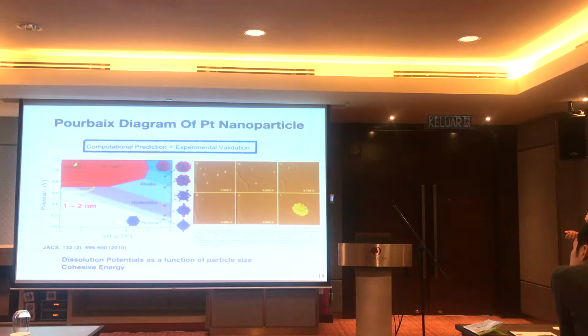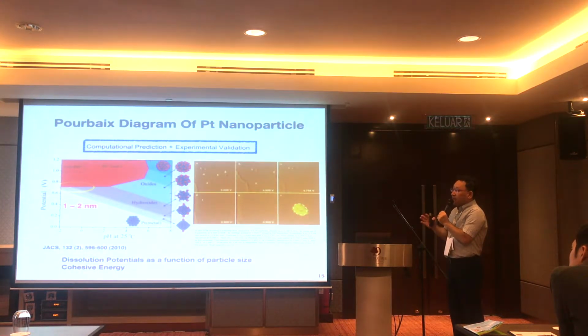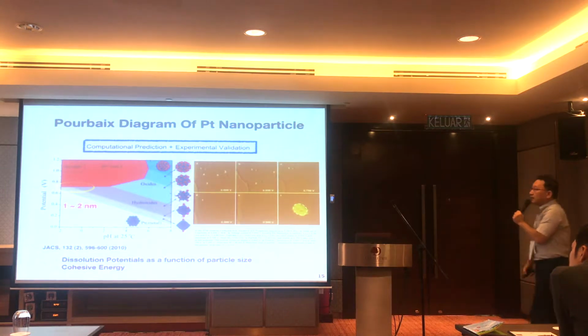This picture shows that platinum nanoparticles dissolve at 0.7 volt. In the meantime, bulk platinum, the wedding ring, right, dissolves only in strong acid solutions. They only dissolve above 1 volt with respect to the standard hydrogen electrode. But a nanoparticle of this size starts to dissolve at 0.7 volt, which means there is a huge decrease in the electrochemical stability, right? You know that electric vehicles driven by hydrogen utilize platinum as a catalyst material. But in fuel cells, mostly the potential window and the pH window are very strong acid solutions and above 1 volt, which means platinum nanoparticles of this size should not be utilized as catalyst materials. Otherwise, we need better materials than platinum.